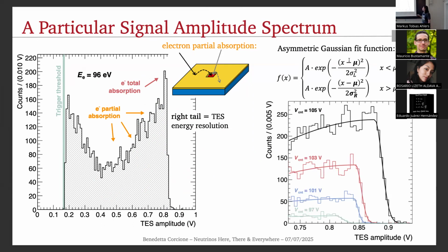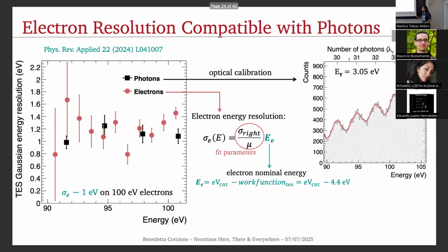And in particular, we care about the right standard deviation to understand the energy resolution of the device. Fitting all these different histograms, we found an energy resolution for electrons of 1 eV on 100 eV electrons. This is how we obtained the resolution. It is defined as the ratio between the right standard deviation obtained from the peak and the mean value of the peak, all multiplied by the electron nominal energy.